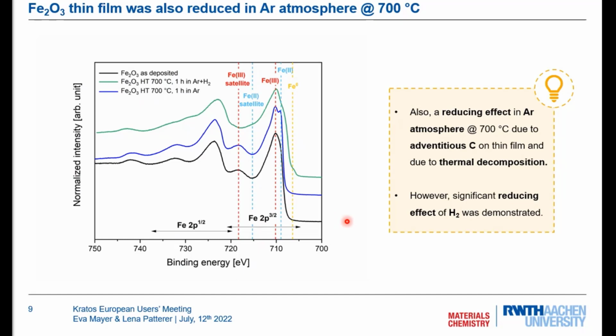However, if you compare the experiment with argon and hydrogen and just argon, you can see that we definitely had a reducing effect of the hydrogen. And so we know that the experiment works. We can see a reduction with hydrogen.